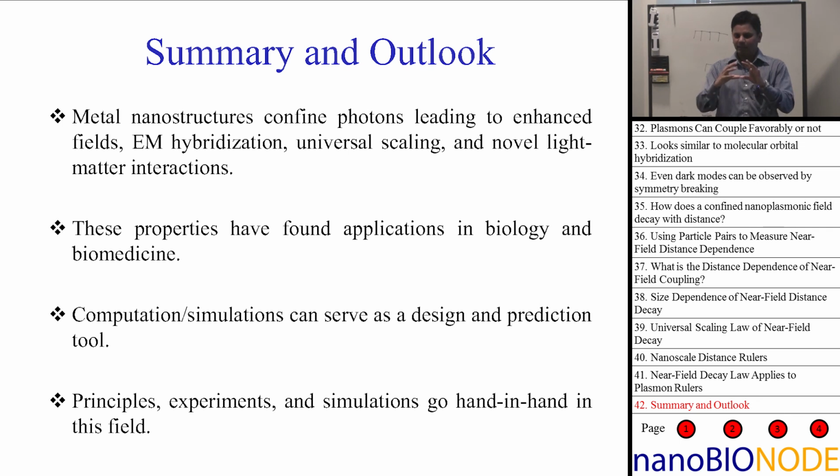But one thing to remember is, at least for small enough structures, 3 or 4 particles, you can't break the problem down into pairwise interactions. The entire chain has one characteristic frequency of oscillation, and not just one, several. You have different modes that arise in this chain. You have a dipolar mode that involves a charge displacement across the entire chain. You have quadrupole modes where charges are built up in the middle of the chain, and so on, and you have higher and higher order modes. So you have certain normal modes in this chain which arise from coupling between all particles. So the entire configuration matters.